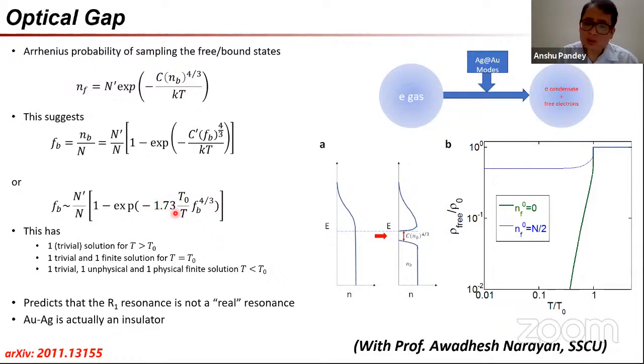And what this shows is that below a certain temperature, a large number of these electrons within the system have a tendency to localize. So in other words, what this sort of model predicts is that this material would actually not be a real conductor at all. This would actually be an insulator. It suggests that we have a significantly reduced electron density in the system.